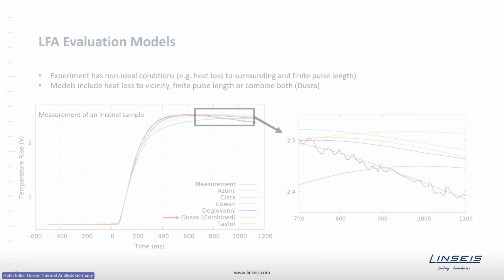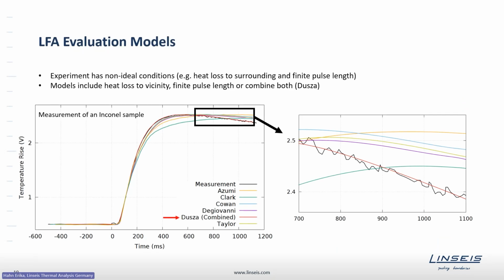So I mentioned before that we use this, let's say quite simple formula of thermal diffusivity calculation with a constant sample thickness and half-time rise. It's not as simple as shown on the first line of the laser flash, so we do not evaluate the curves graphically, but there are some mathematical and physical models behind that, being able to fit the evaluation model to the data, because basically the laser flash setup assumes an adiabatic state, so the ideal state.